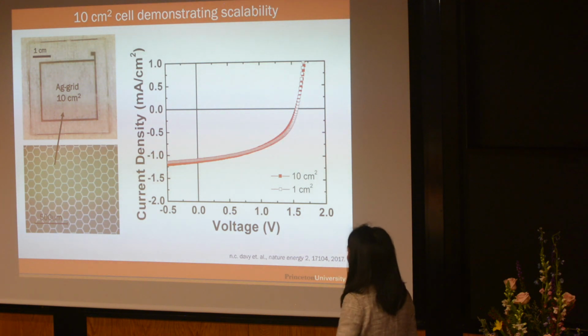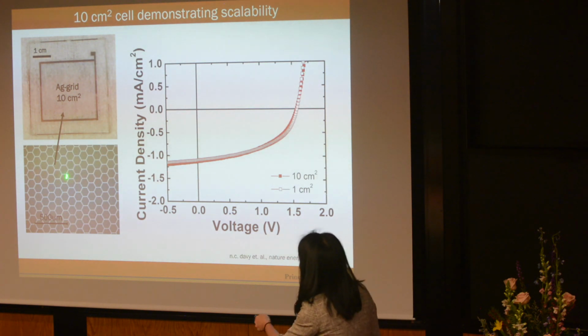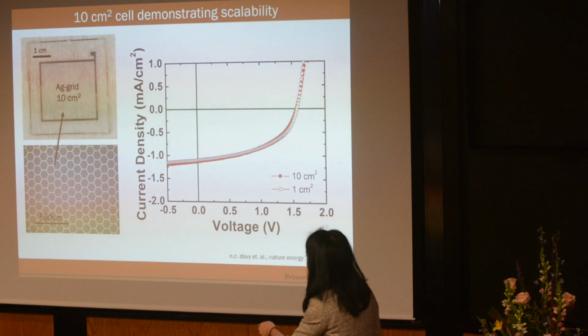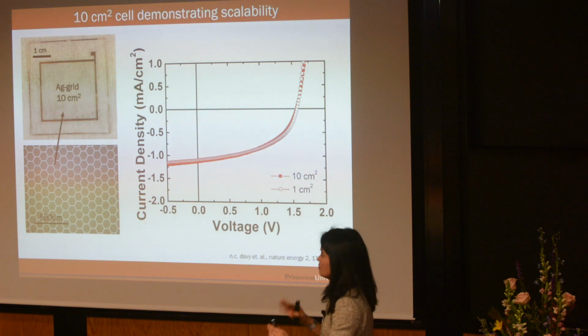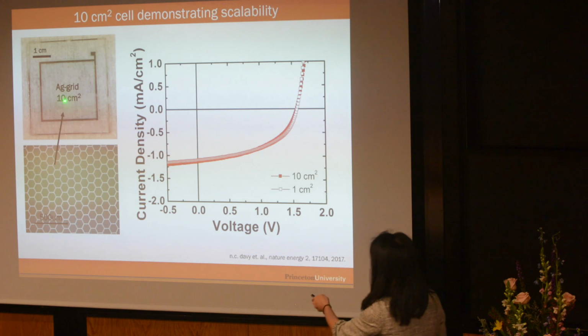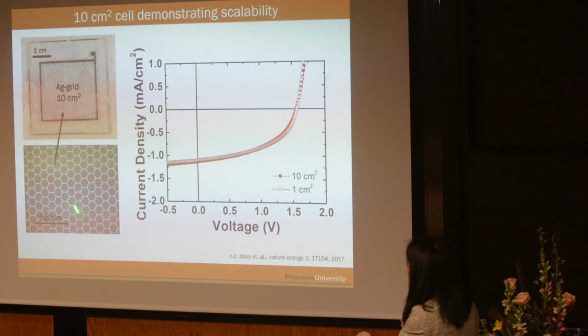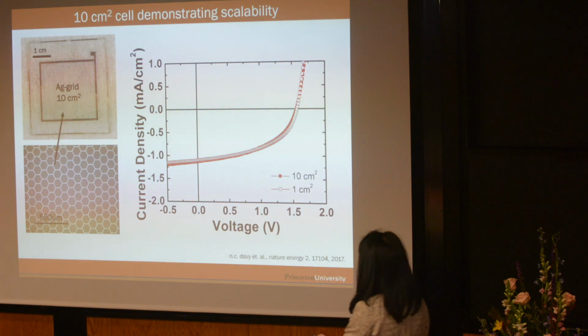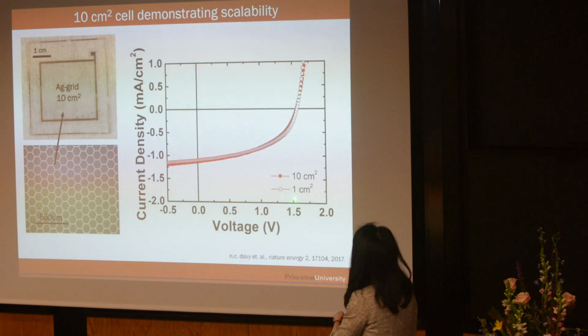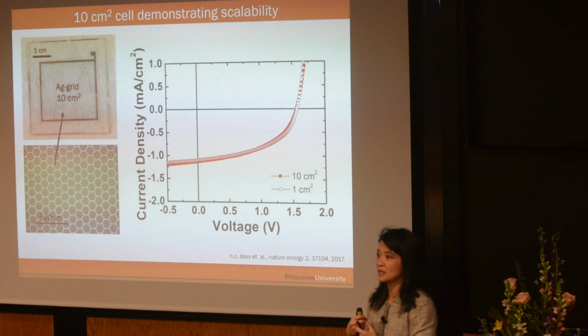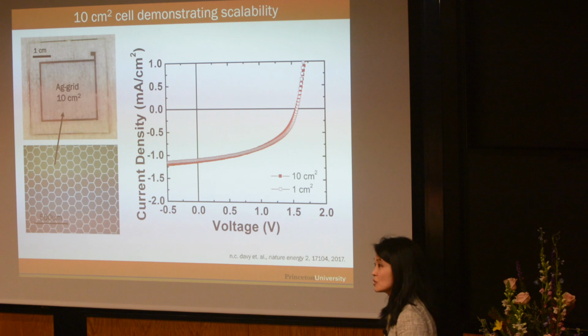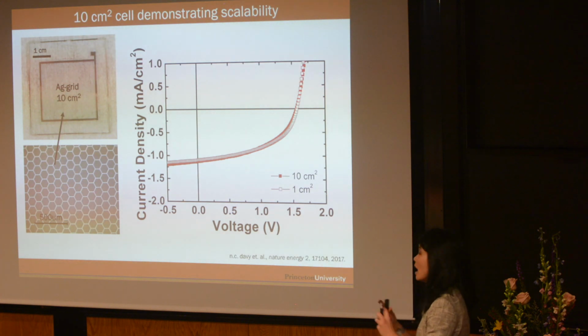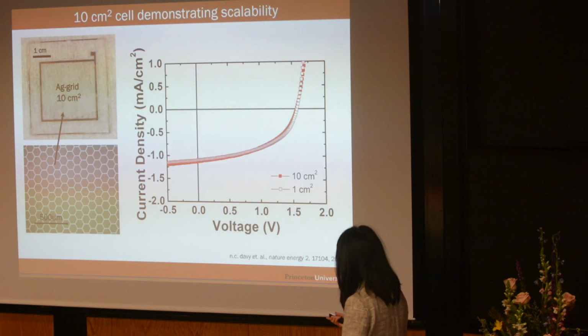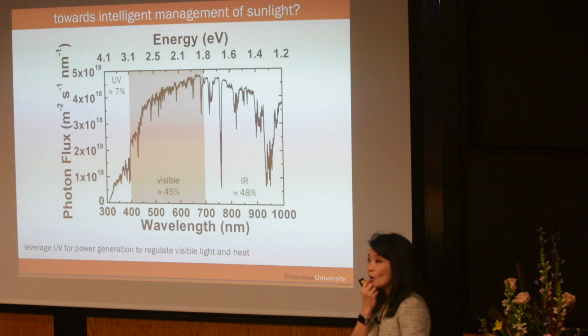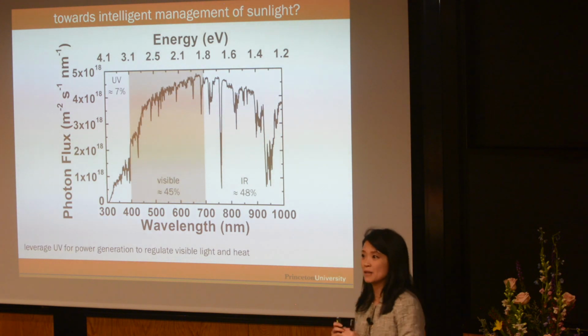So here, basically, what we have is a silver grid. And so this is a zoom-in version of the silver grid, right? And so it's a honeycomb pattern. It's not really visible to the naked eye. But this is now sufficiently conducting. And we can make cells with this. And you can see the 1 centimeter and the 10 centimeter squared cell. Again, it lies right on top of each other. So we can make 10 centimeter squared single junction cells now. So hopefully I've convinced you that we can make these transparent solar cells.